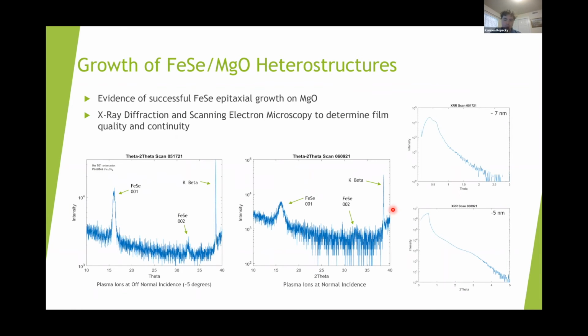From there, we wanted to further study the transition into the superconducting phase for iron selenide. So we began the growth of iron selenide magnesium oxide heterostructures. And this is in order to further study through terahertz spectroscopy, in which MgO is optically clear in the terahertz region. And so from this, we studied two different samples, where the plasma ions were off incidence, about 5 degrees off of the